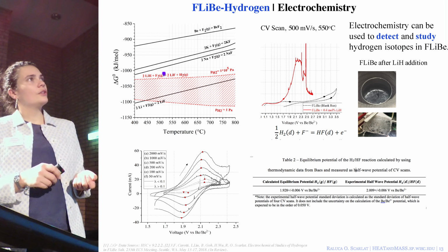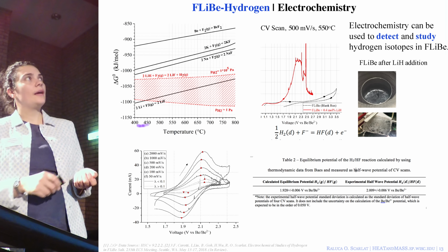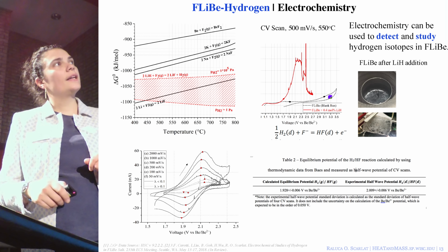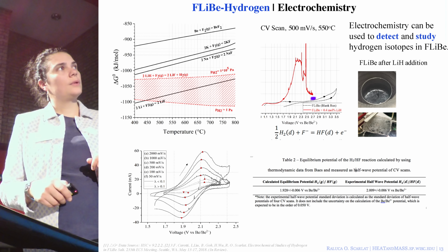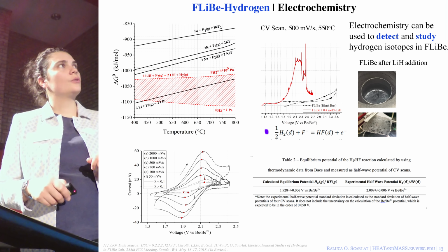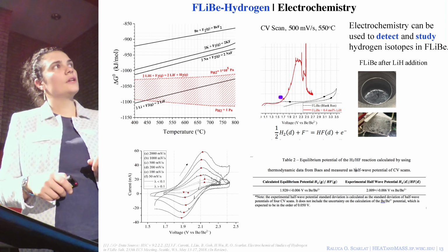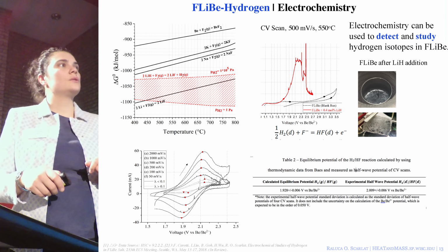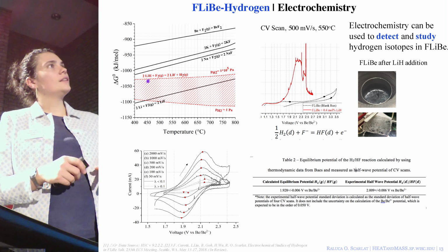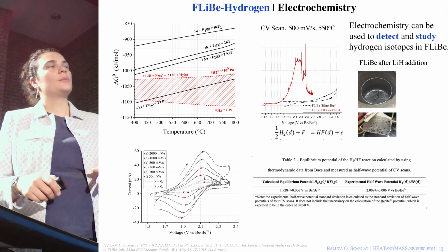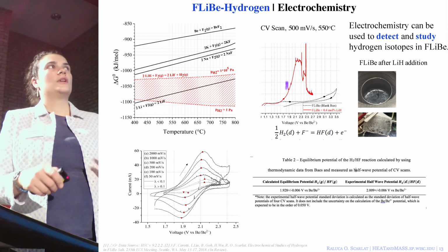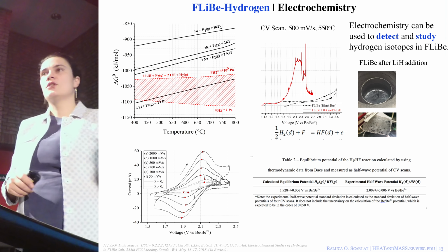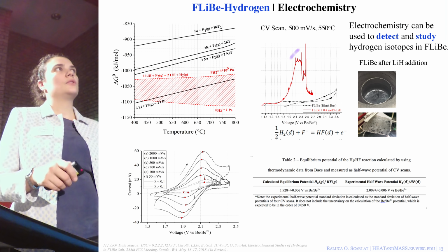And then hydrogen gas, we would then electrochemically react at the surface of the platinum electrode. And so here in black, you see a potential applied to our platinum electrode, and on the y-axis is current. And we see no signal around the potential where we would expect to see hydrogen occur. And after we add lithium hydride, we sweep again the potential and we see a current. So that means that we are indeed, as thermodynamic data predicted, producing H2 in solution, and we're able to manipulate it.